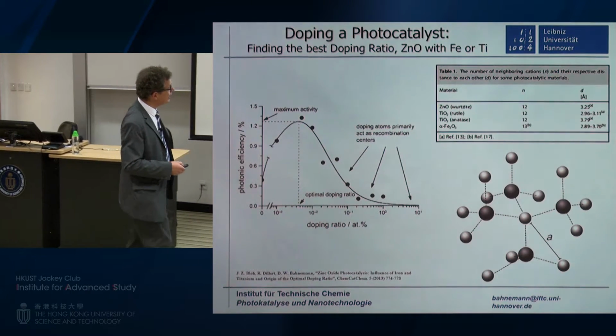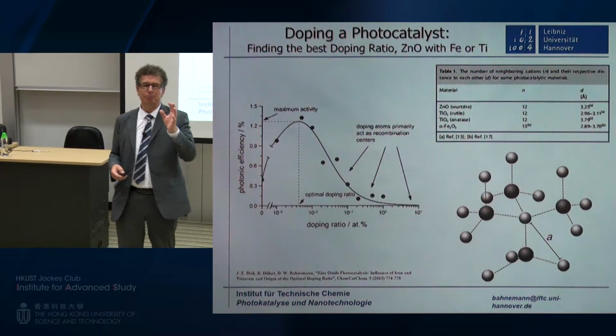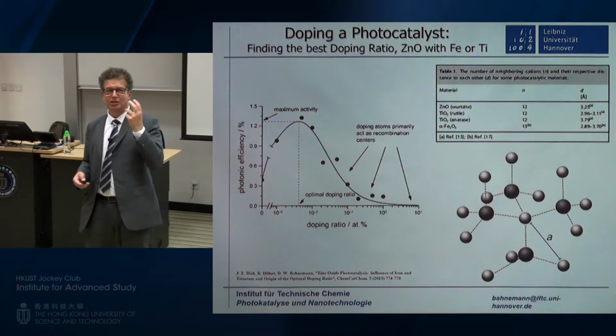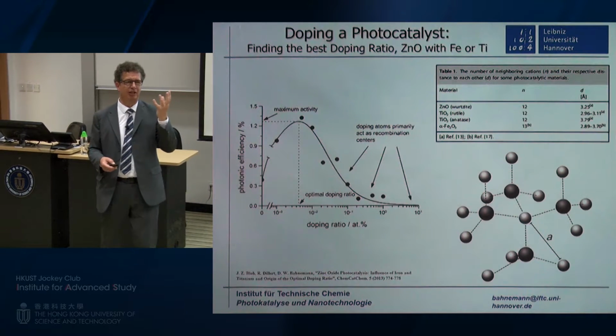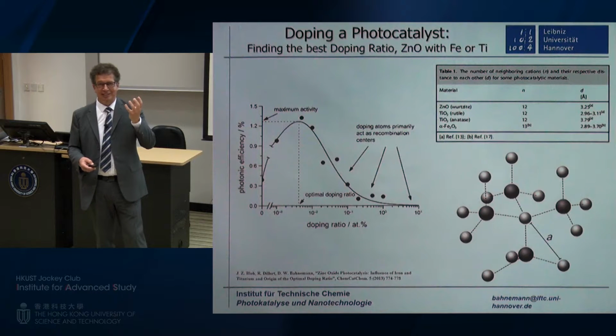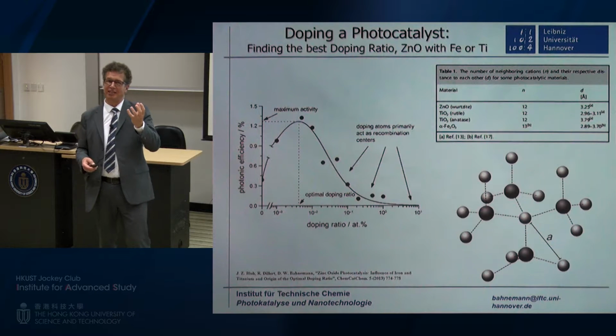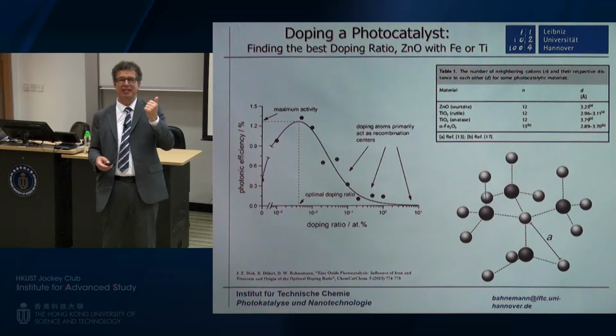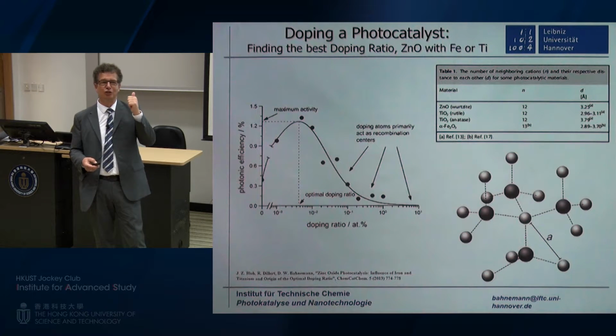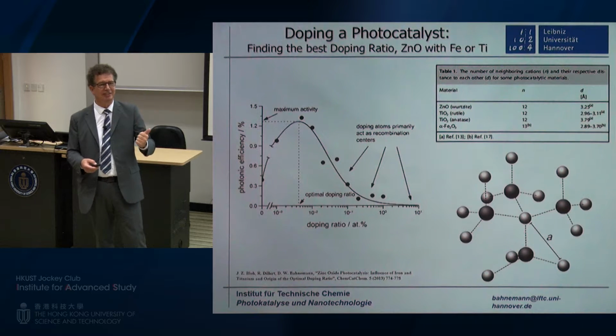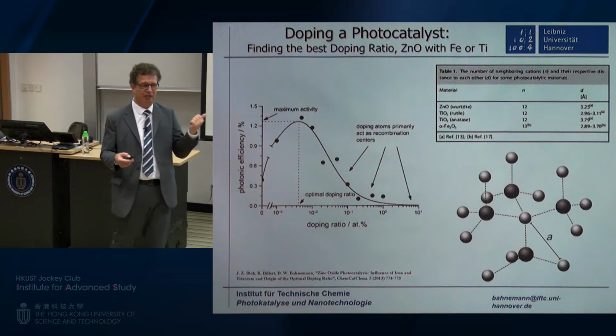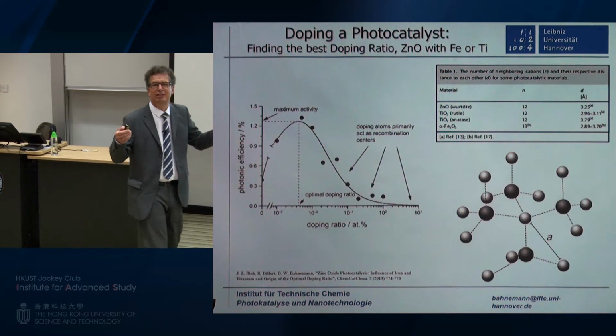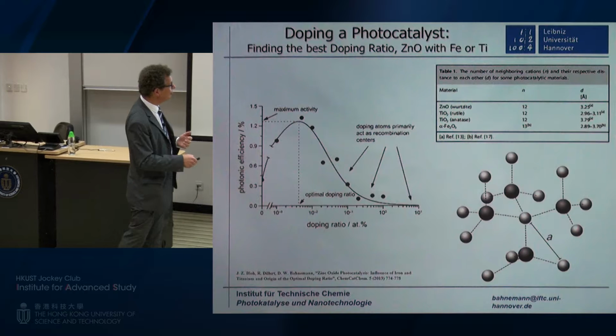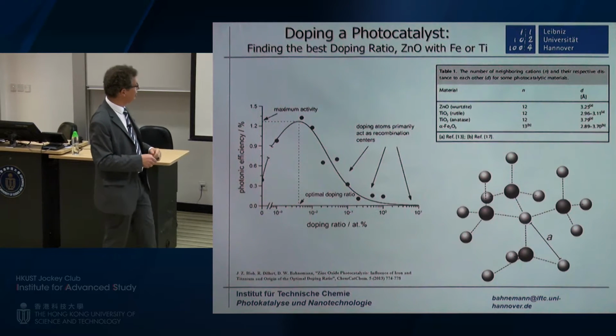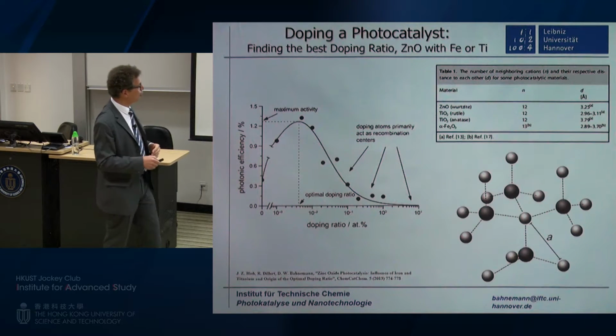So we looked into this and we developed a simple mean-field model. What is a simple model for doping of nanoparticles? Well, first guess: if doping should have any effect, you should have at least one dopant atom per particle. If there is no dopant atom in a particle, then doping cannot have an effect on this particle. I think everybody in this room will agree to this. So this is the first thing we put in this model. So nothing in there, no doping.